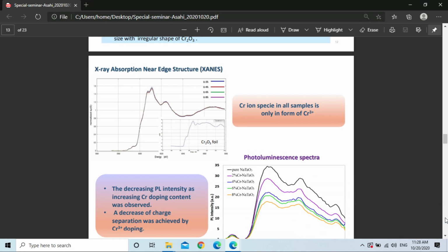So we would like to know which chromium ion species exist in our sample. We measured our samples by X-ray absorption near edge structure, comparing with standard chromium oxide foil. We can see that all samples have peaks that match and fit with the chromium oxide foil. It means that the species of chromium ion in all samples is chromium 3+.